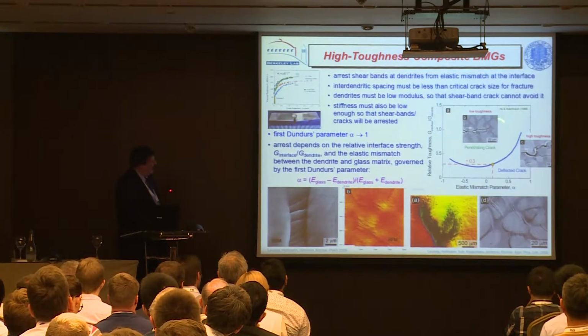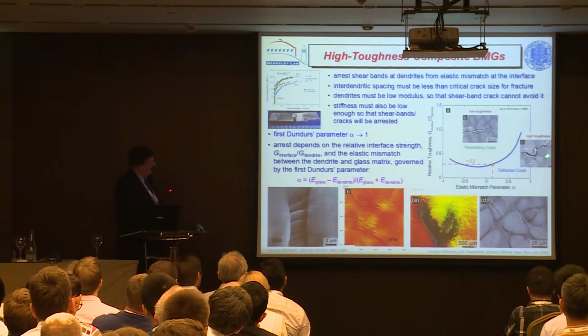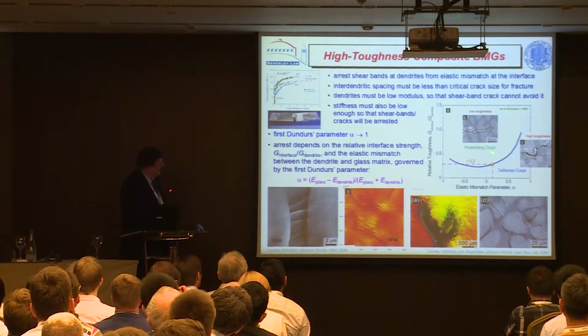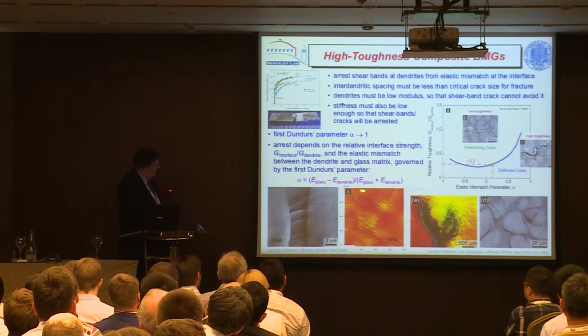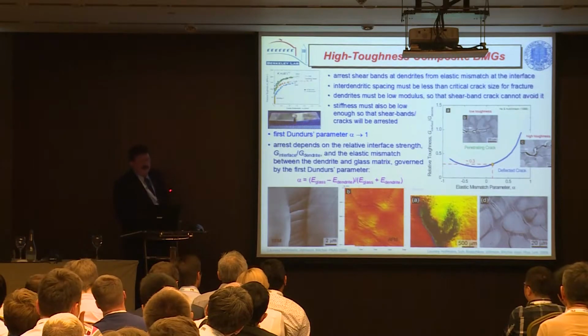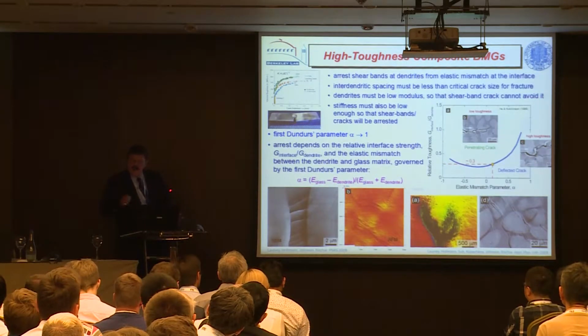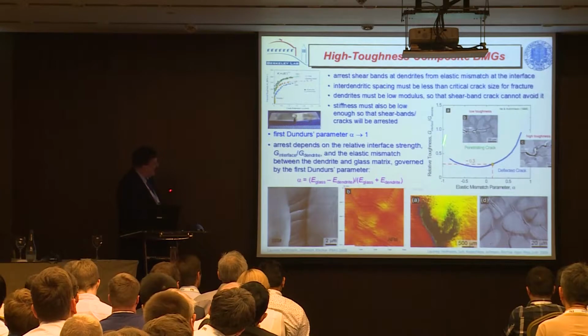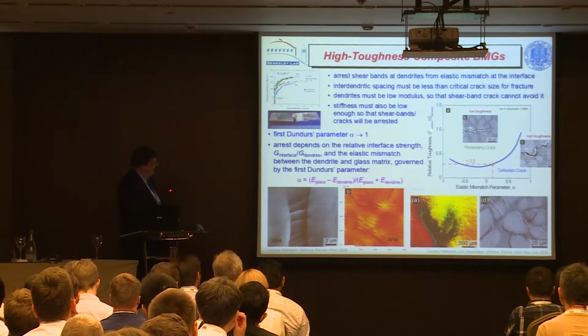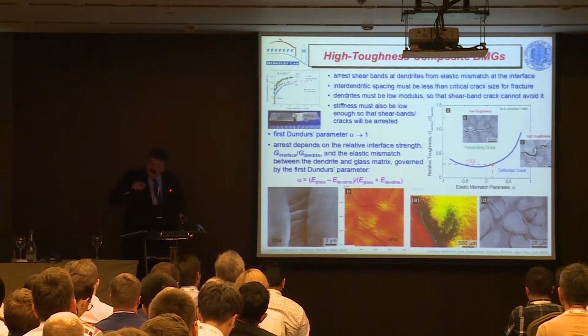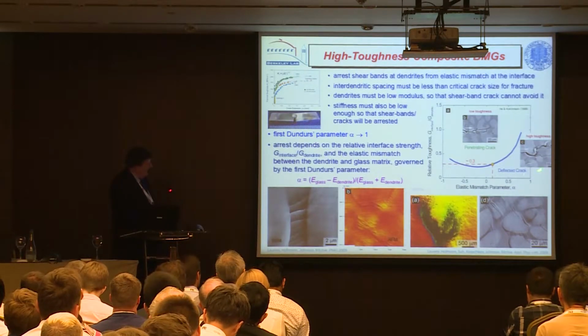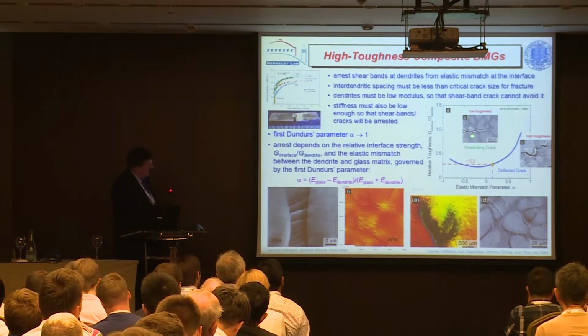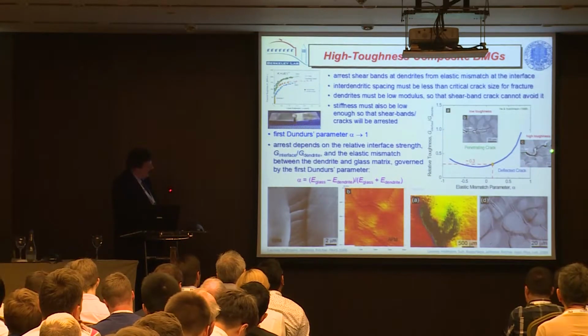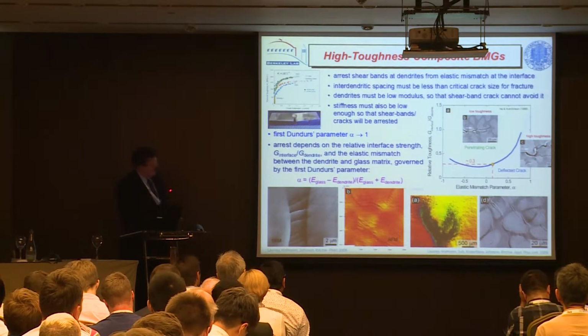And if you look at the He-Hutchinson plot of a crack penetrating or arresting at a dissimilar metal interface, it's a function of the elastic mismatch across the interface, which is simply the difference divided by the sum of the respective moduli of the two materials. This is the first Dundurs parameter. And on this axis, it's basically the interface toughness divided by the toughness of the material that the crack is going into. You want to be in this region here for the crack not to penetrate. You want it to arrest or go around the particle.